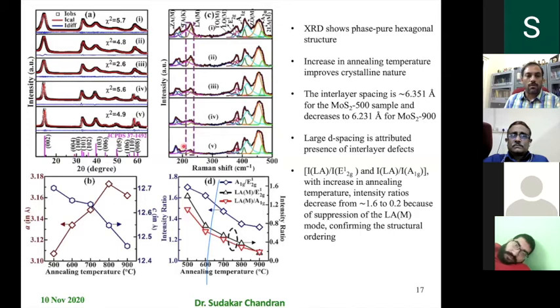This particular one shown in the box here is a defect mode, a defect activated mode. As you anneal it, this intensity goes down, and that can be used as a quantification for the presence of defects. Of course, you can see with annealing, the distance between the layers changes, or the lattice parameter changes. It decreases, whereas the lattice parameter a increases. So the annealing effect, where the defects are controlled, has an influence on the lattice parameter. And this is the particular way you can analyze the Raman spectra to infer how the intensity ratios of the normal vibration modes change with the defect modes.